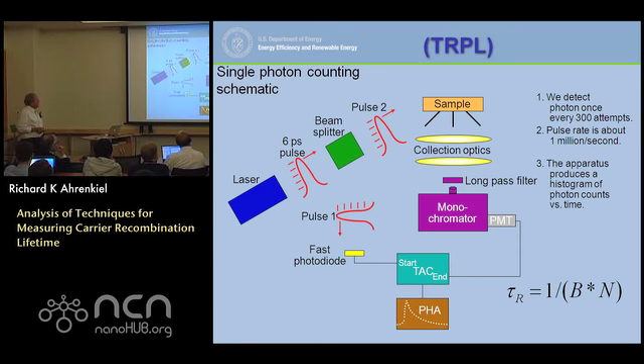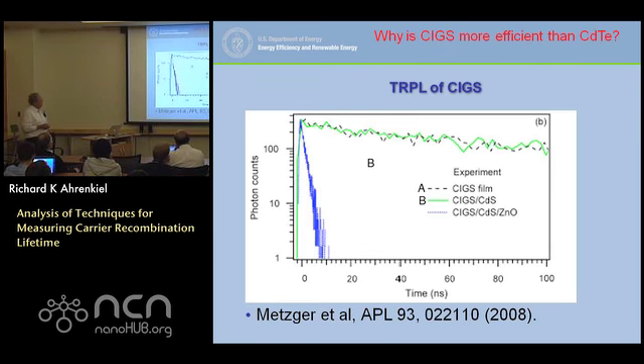Now, the way the system works here is the photon emission rate is much smaller than the repetition rate of the laser. So typically every 1,000 events or so we'll pick up one photon. It'll get amplified and it'll come out here and it'll start the stopwatch, which we call the time amplitude converter. This is really a ramp, and so a voltage ramp starts as soon as the laser goes off, and it stops when a photon gets there, and the height of the ramp is an indicator of the delay time. That delay time goes in a bin, so every photon we collect, we catalog, we put in a bin, and then as time builds up, we build a histogram of the decay events. So out of that, we are able to get the lifetime of the material.